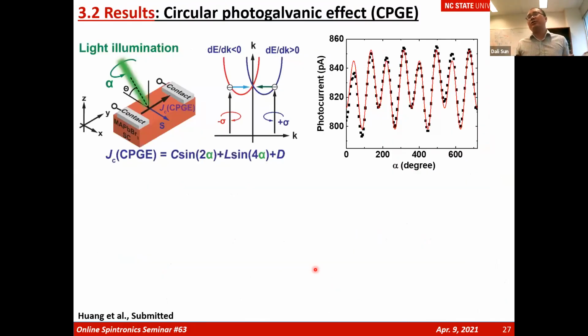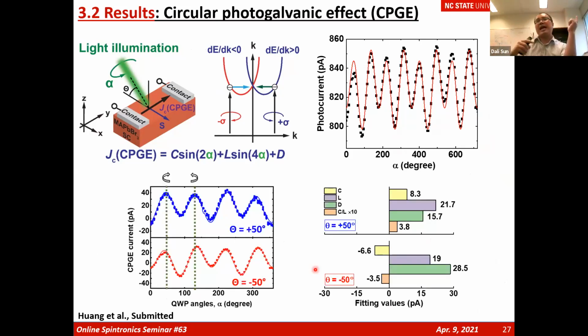So that's our motivation for our studies. We do exactly the same thing. We fabricate the best single crystal we can. We shine circularly polarized light, measuring the photocurrent as a function of circular polarization. We see a very nice oscillation of photocurrent as a function of circular polarization. If we change the angle from positive incident angle to negative incident angle, because the spin polarization reverses, the transverse photocurrent reverses too.